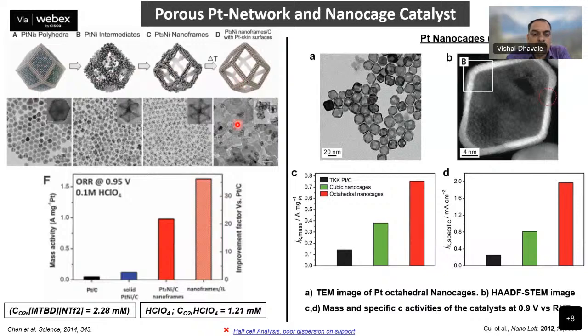Which we can then support on different types of carbon material. This kind of material gives a benefit and improvement in the activity. You can see over in the graph, compared to the Pt/C, platinum supported on carbon, that is the state of the art catalyst. You can see the improvement factor, almost more than 30% improvement in the performance compared to the state of the art catalyst. So other than that, the activity can be noted over here.